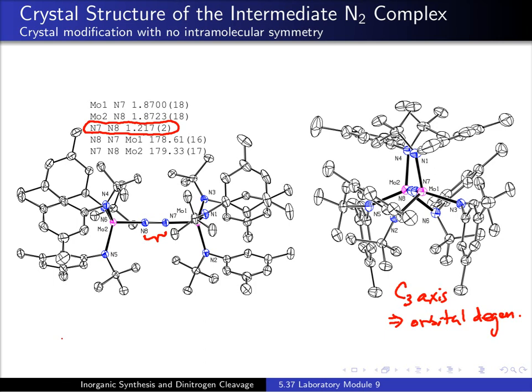One more thing to mention in the structure of the bridging N2 complex intermediate is that you can see that the small N2 molecule is capable of bridging between the two molybdenum centers, and the six tert-butyl groups in the system are brought very close together, and there's steric clashing here.